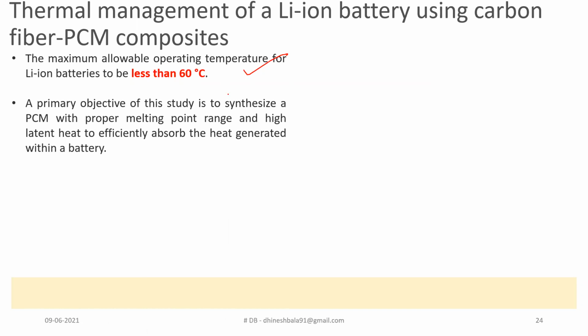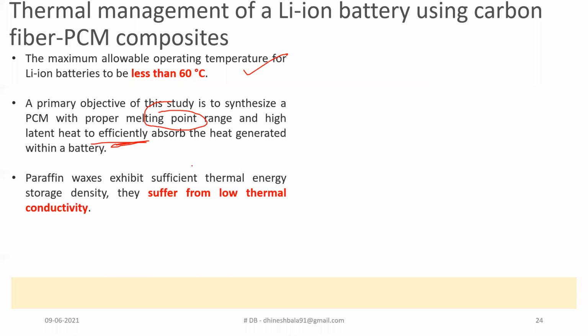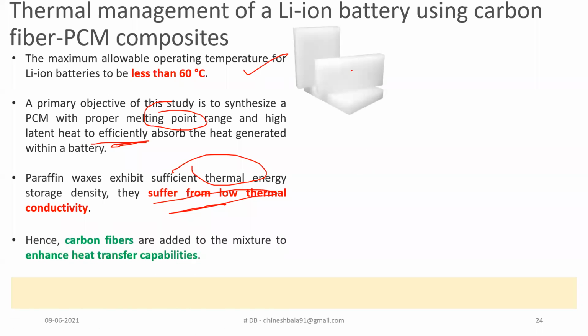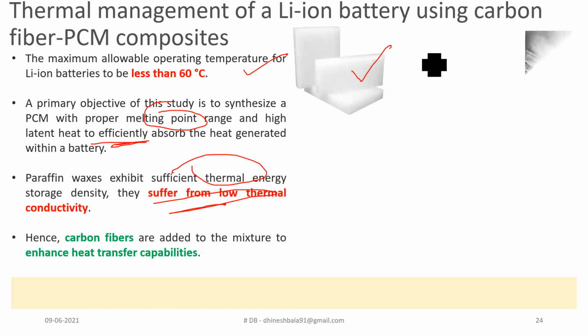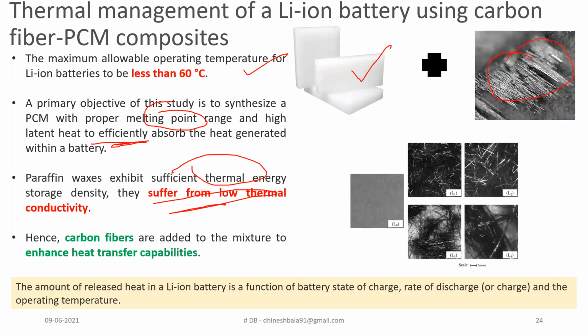So the primary objective of the study is to synthesize a PCM with proper melting point range and high latent heat to effectively absorb the heat generated within the battery. So the paraffin wax exhibits sufficient thermal energy storage density but suffers from low thermal conductivity. So in this particular study, they have taken paraffin wax along with carbon fiber, and they have tried to melt it and add a few percentage of carbon fiber along with it.